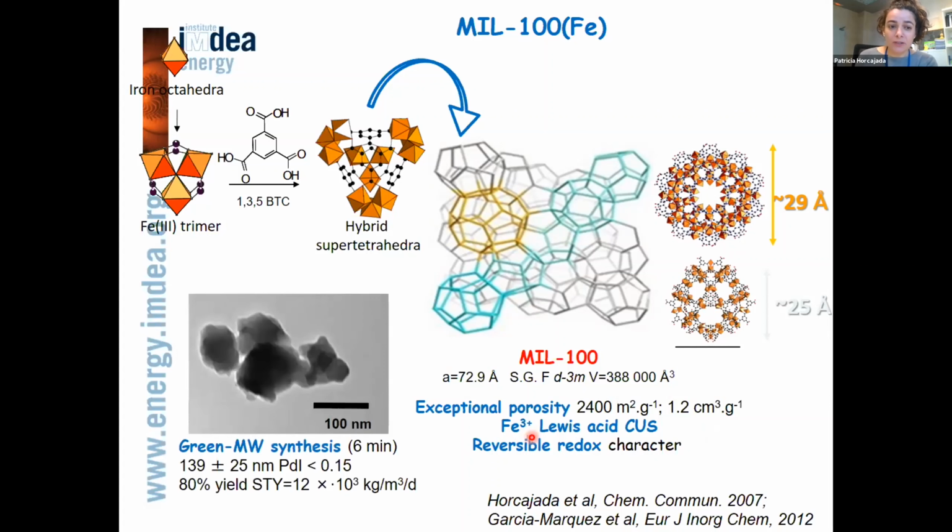In addition, we are able to produce MIL-100 in the form of nanoparticles of around 140 nanometers, compatible with intravenous administration, reaching a very important space-time yield, so a high production, by a simple, very fast, and totally green microwave synthesis.